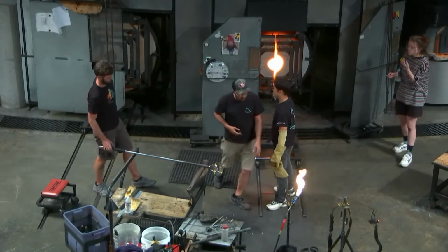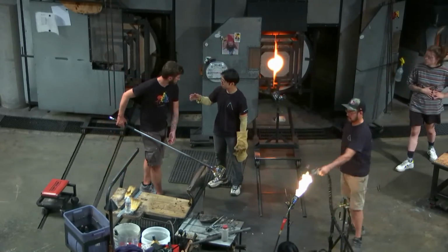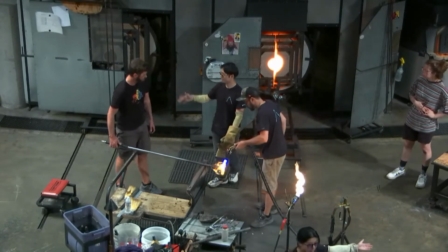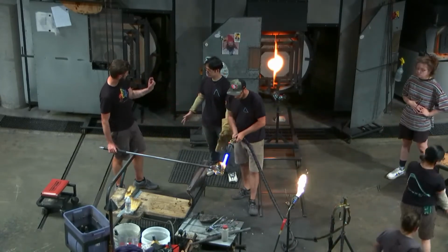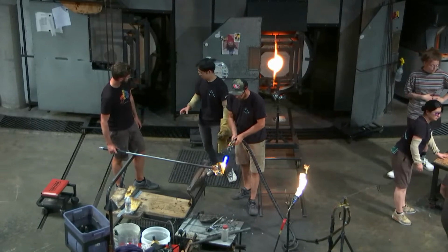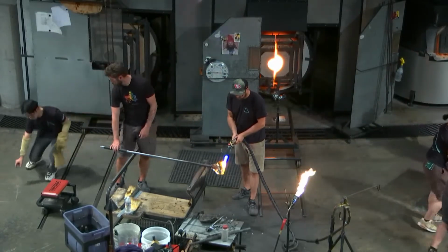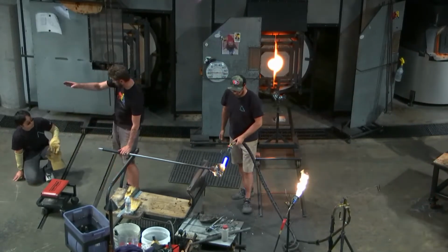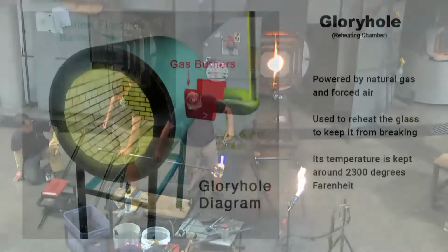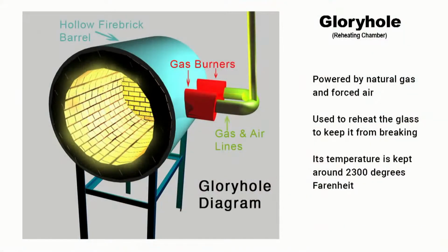So the large drum-shaped oven that we will work in and out of once we pick up this pattern is known as a glory hole, and it's just a place where we reheat the glass. There's no glass inside of the glory hole. It's a 2300 degree oven, and it's powered by natural gas and forced air, and it's used only for reheating to prevent thermal shock. And that's what the inside of your glory hole will look like. It's bricks, ceramic bricks, or fire.